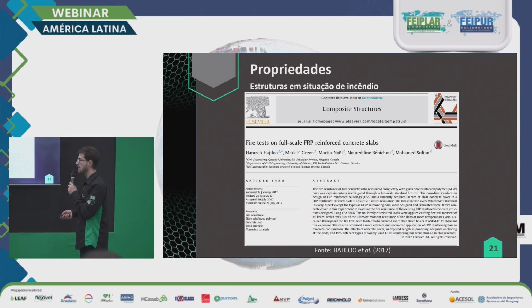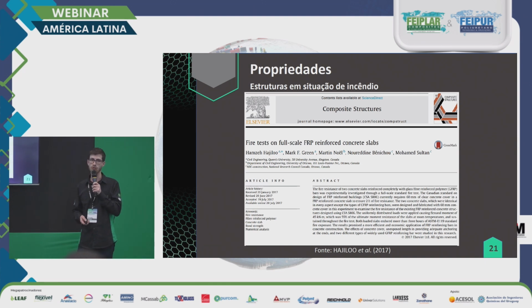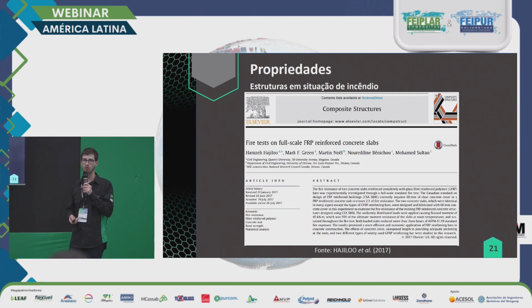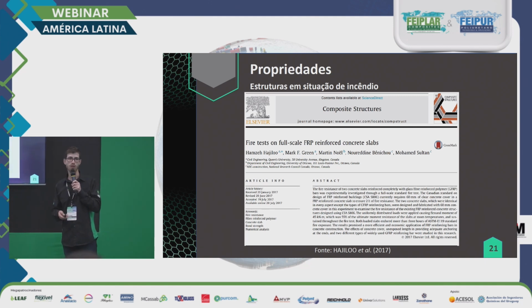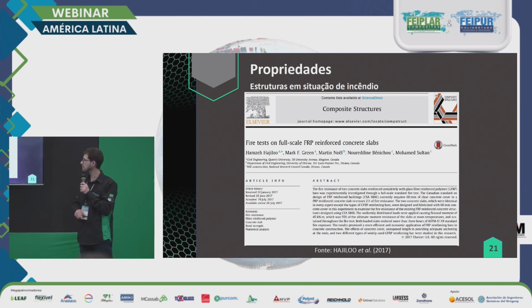The lengths that they used, the fire curve. We have two curves for that. The most commonly used is ISO 834 or ASTM E119, with different curves depending on the type of fire we are dealing with. So curves for residential fires above 1,000 Celsius, and that's the one that was used in this test.